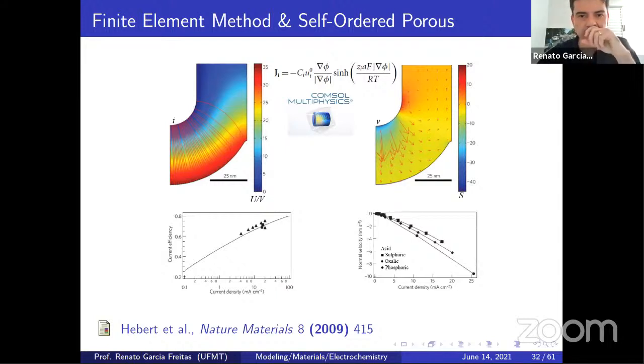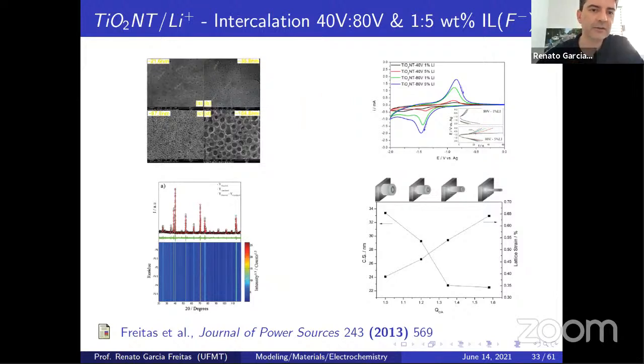So as soon as we read this paper, we induced stress as well in titanium oxide nanotubes, applying different voltage values, and changing the percentage of ionic liquid, which was the precursor of fluoride to obtain fluoride species. So we studied two systems, 40 volts, 1% ionic liquid, and 5%, 80 volts, 1% and 5%. So we have porous nanotubes with 20 nanometers, 36 nanometers, 97 nanometers, and 164 nanometers of diameter. We obtain the titanium oxide nanotubes with Rietveld refinement, for sure, and we obtain all the structure parameters, and you obtain here